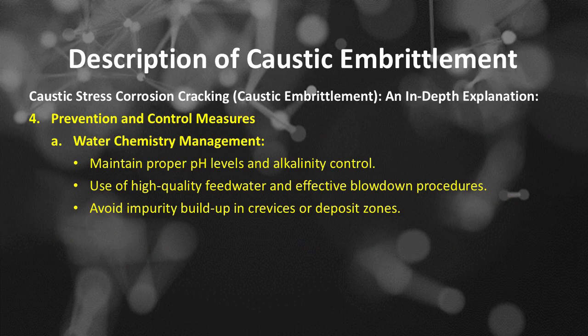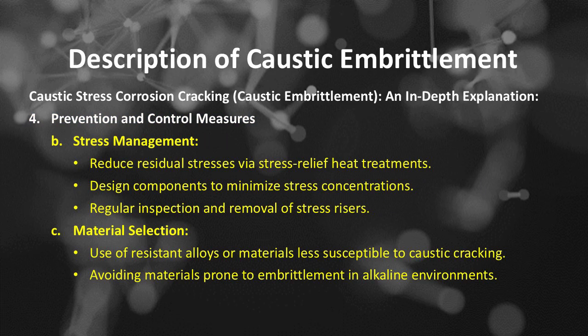Number 4 is prevention and control measures of caustic embrittlement. Number A, water chemistry management. Maintain proper pH levels and alkalinity control, use of high-quality feedwater and effective blowdown procedures. Avoid impurity buildup in crevices or deposit zones. Prevention and control. Number B, stress management. Reduce residual stresses via stress relief heat treatments. Design components to minimize stress concentrations. Regular inspection and removal of stress risers.